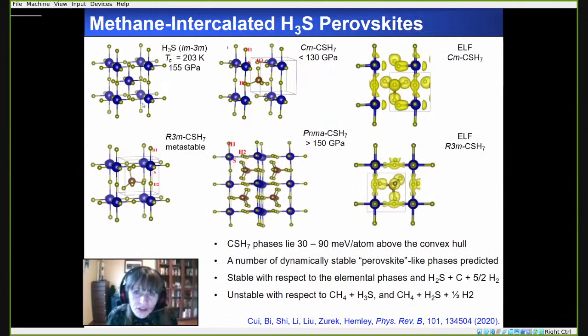Another system that we have looked at is ternary hydrides, because not all of the binary hydrides have been explored to date. As I mentioned previously, the H3S phase has been shown to have quite high TC. So it was a good idea to think of mixing hydrogen sulfur with other elements. And in this case, we chose carbon. Theoretical crystal structure prediction searches were carried out on a variety of CSHN structures. And what we found is that this CSH7 phase stood out to be particularly stable.